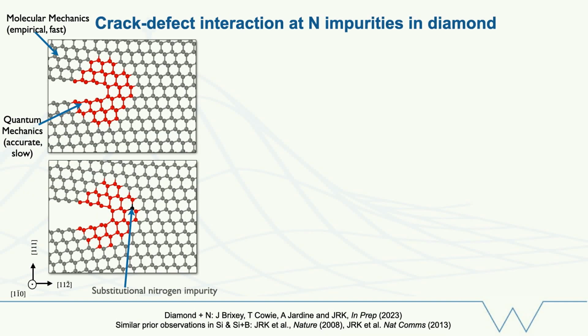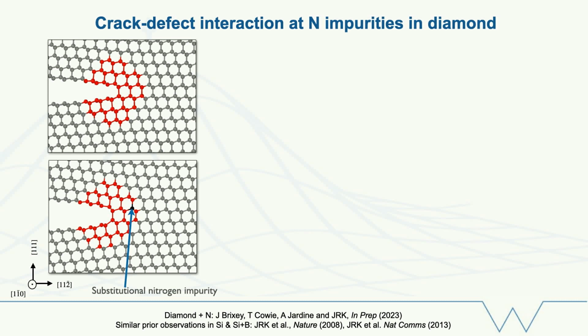A couple of applications to show you what we can do and what we can't do with these approaches. So this one is a fracture of diamond rather than silicon. We're zooming in on a crack tip here. First of all, in pristine diamond, we see again mirror-smooth fracture surface creation. Bonds break one by one and the crack advances.